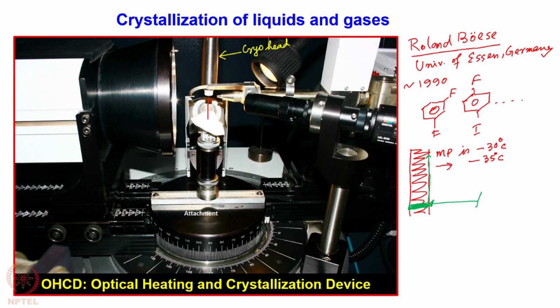And then if somebody moves this molten zone upwards by moving the mirror slowly, by moving the laser upwards, the molten zone moves up and the lower zone again recrystallizes, and this process is done several times. And if suppose the length of this capillary is about 3 centimeters, the laser beam travels this 3 centimeter distance in 2 to 6 hours. So this slow movement of the liquid zone ensures crystal growth inside the capillary as a single crystal.